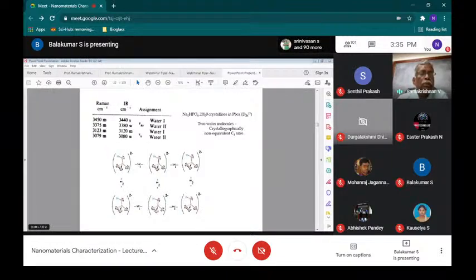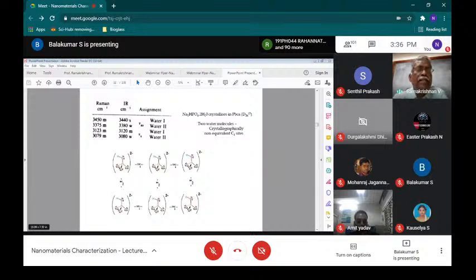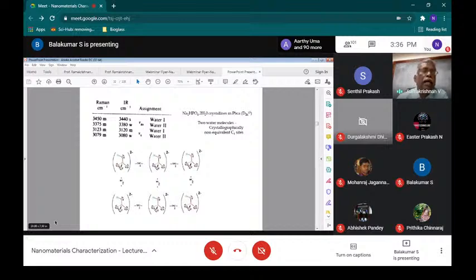So that means this water molecule has a different environment than this water molecule, W1 and W2. If you look at the Raman data, you can see two sets of Raman lines corresponding to water stretching frequencies, one corresponding to antisymmetric stretching, another corresponding to symmetric stretching. So a set of doublets are observed in the Raman spectrum in the stretching frequency region of the water molecule. The reason is that you have two water molecules in different environments, W1 and W2. One is responsible for the layer formation, another is responsible for interlinking the two layers. Next slide.